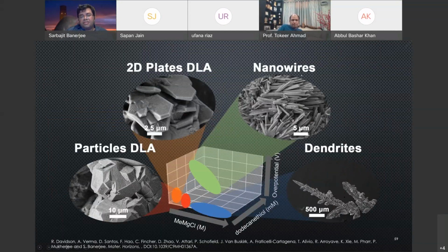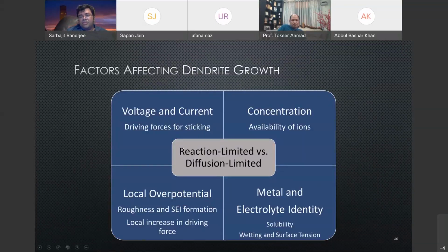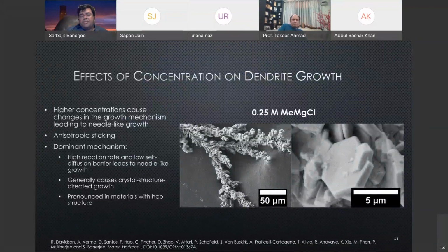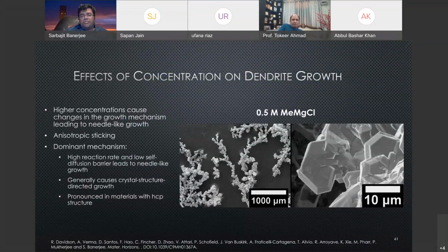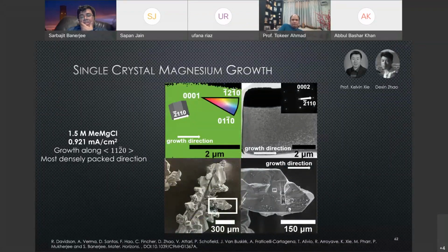Again, 2D deposition in certain regimes, this is ideal. You get these large particles in other regimes, and nanowires in some regimes, and then these dendrites in other regimes. And so there are lots of different factors that control magnesium deposition: voltage, current, concentration, local overpotential, and metal and electrolyte identity. And here are some pretty pictures of the sorts of particles that are deposited. And you can even, in fact, grow large single crystals by this method.